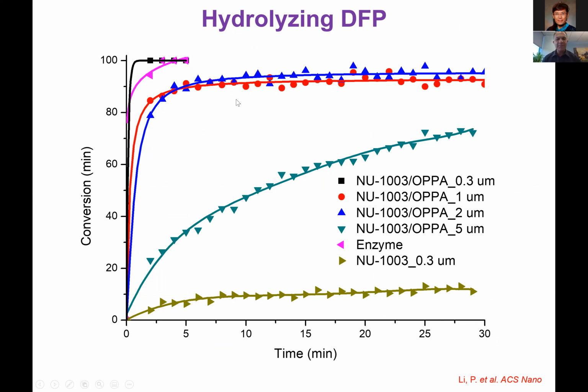and by the way, just for clarification, those lines are not kinetic loss. Those are just to aid your eye to see which data goes with what. But you could see here, when we go to the 300 nanometers, actually our composite is even faster than the free enzyme. I was surprised actually when I saw this.